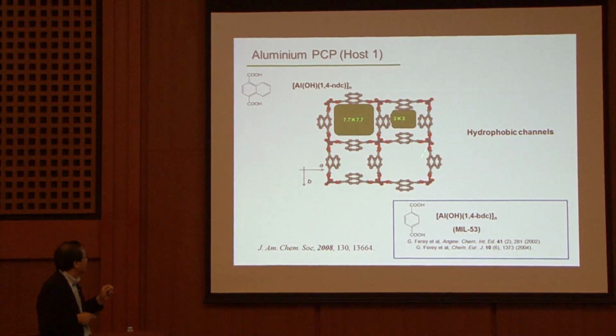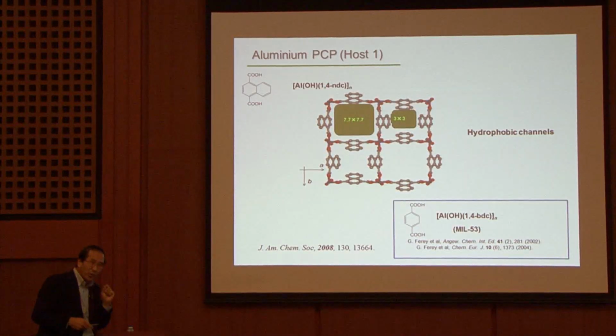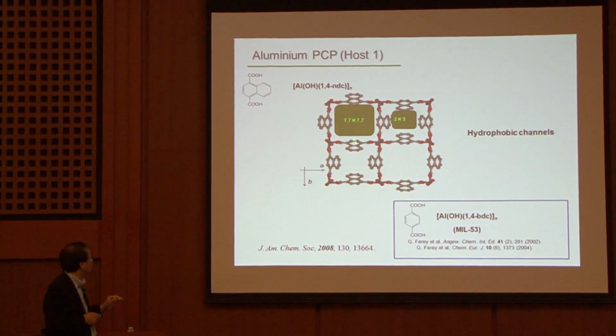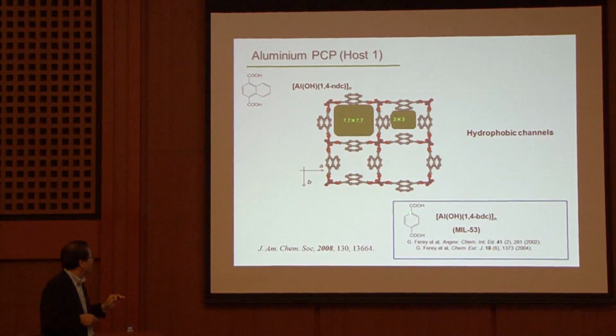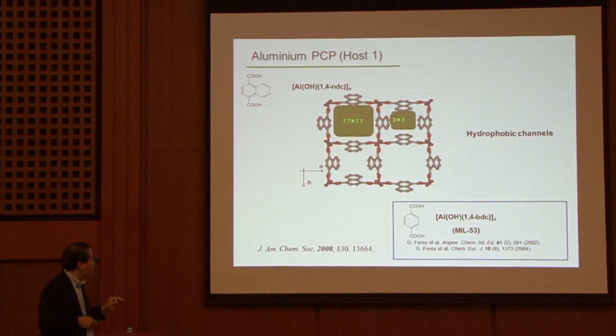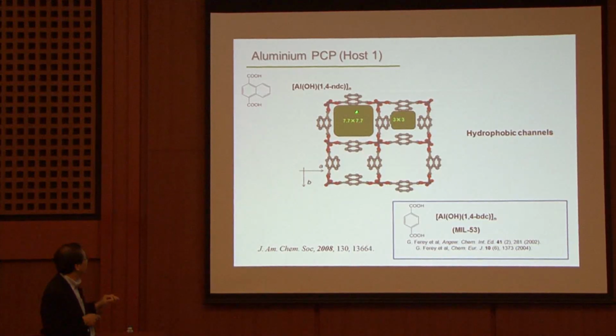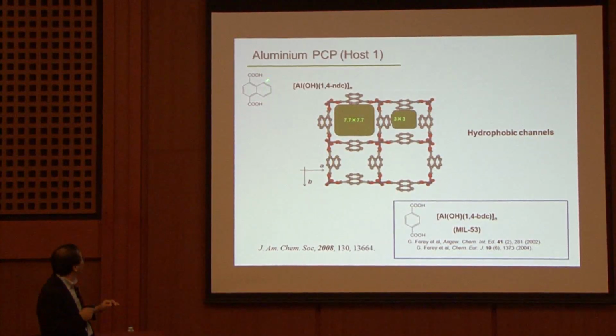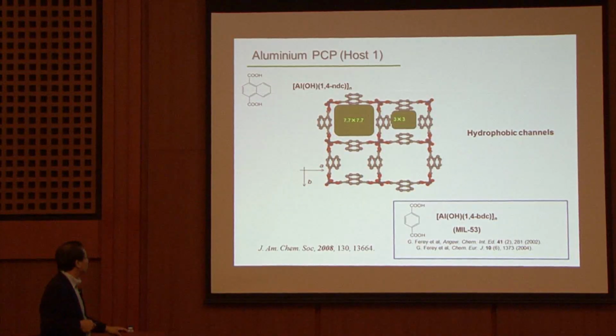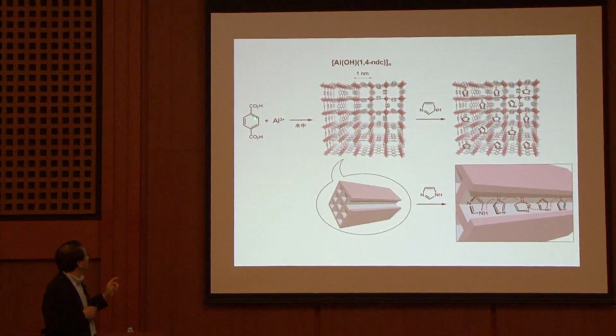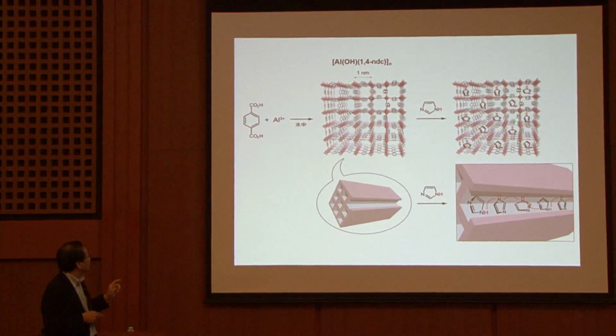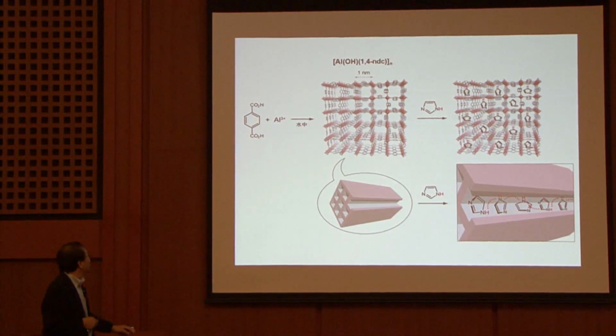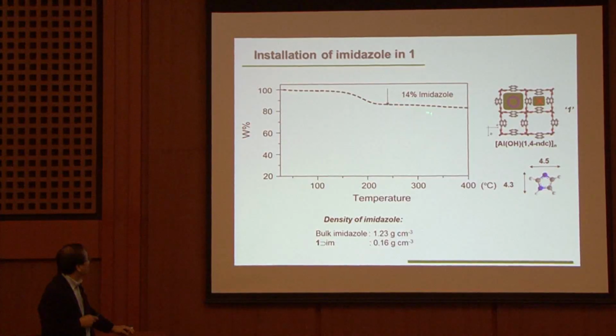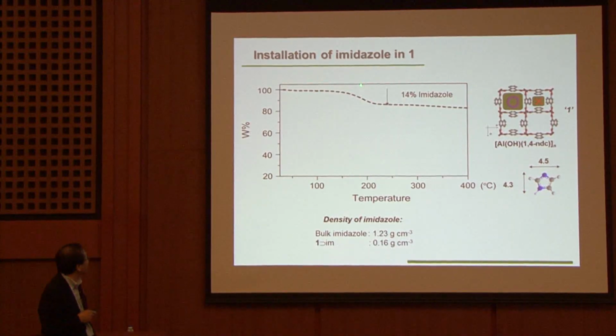The properties of the surface are completely different from this. This has a hydrophilic channel, but this case is hydrophobic because of this site. That's the point. So we accommodate the imidazole in the cavities. This is the thermal stability in this case. Over 100 degrees Celsius, the imidazoles are still accommodated in the channels.